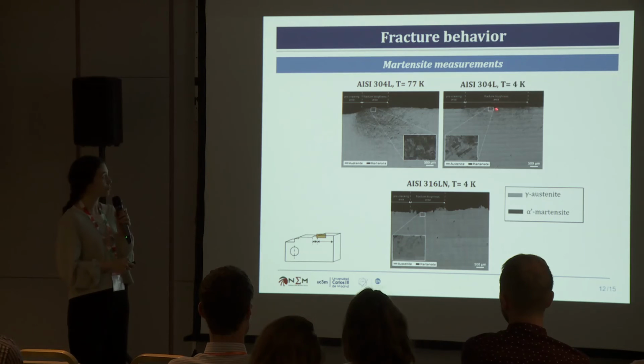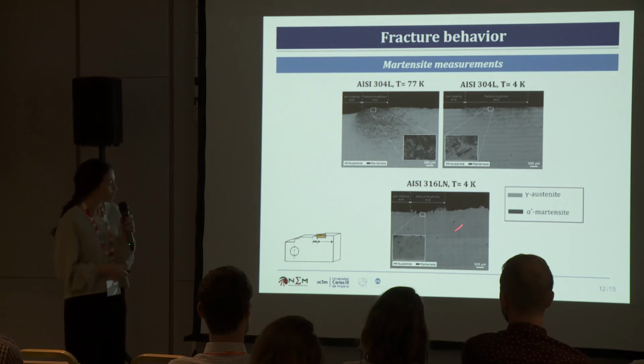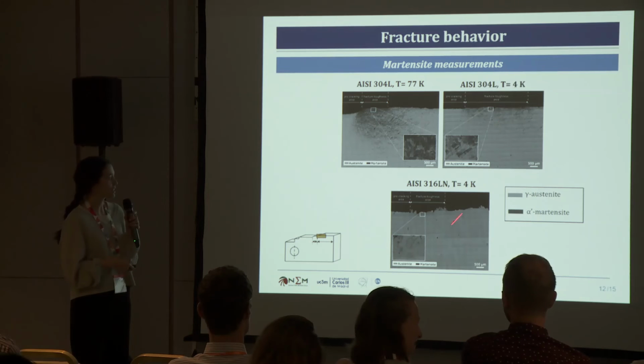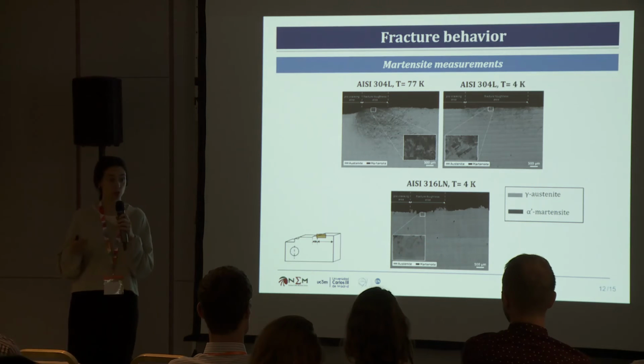Now, if we compare at 4 Kelvin the AISI 304L with the AISI 316LN, I hope you can see, maybe not super well, but you can trust me, that here we have more martensite than here. And it makes sense because we saw that the transformation was higher for the AISI 304L than for the AISI 316LN.